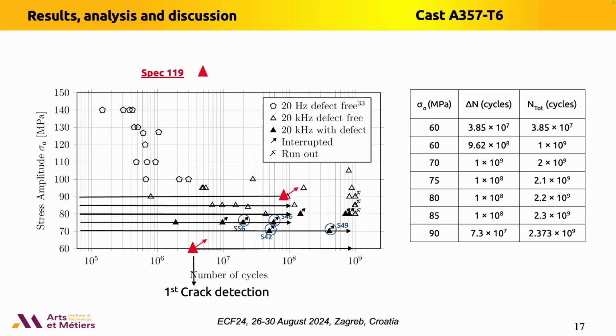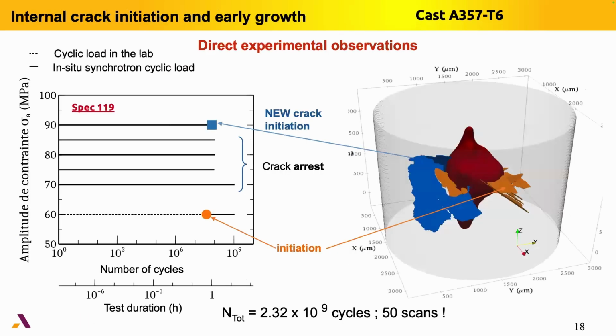So now, if we try to understand why we observe that. In fact, if I summarize graphically the loaded history of this specimen, it is illustrated here. You have the stress amplitude applied and the number of cycles. For information, you have here the duration of the test at 20 kilohertz to show that the test is realistic in 1 day.